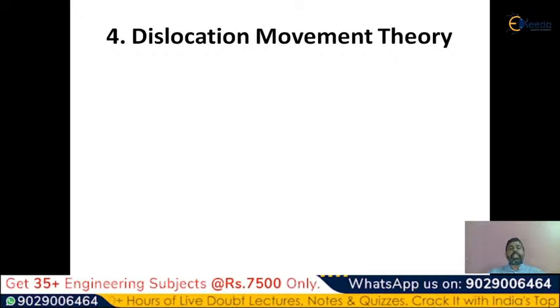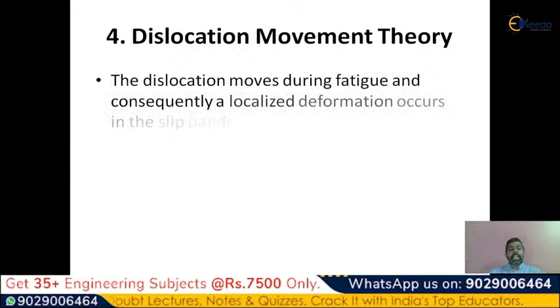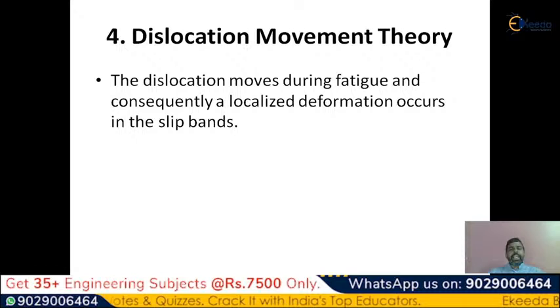So what is important here? The dislocation movement must be arrested. We cannot say that dislocations can be avoided. I repeat this particular statement, which is very important. We cannot avoid the dislocation. We can restrict the movement of the dislocation only. The next question is, what will happen if the dislocation movement is restricted? Because of the restriction of dislocation movement, the cracks can be reduced at least up to some percentage. I cannot say that the cracks can be reduced up to the maximum percentage, but we can say that the cracks can be reduced.